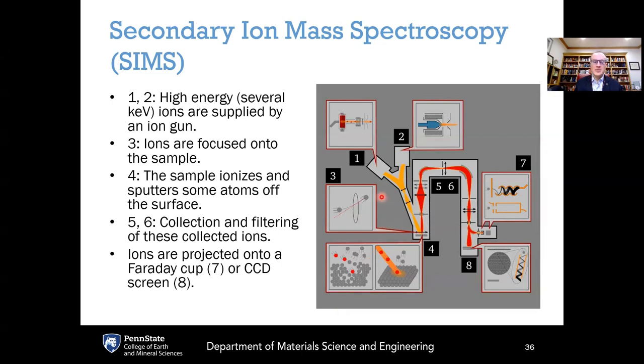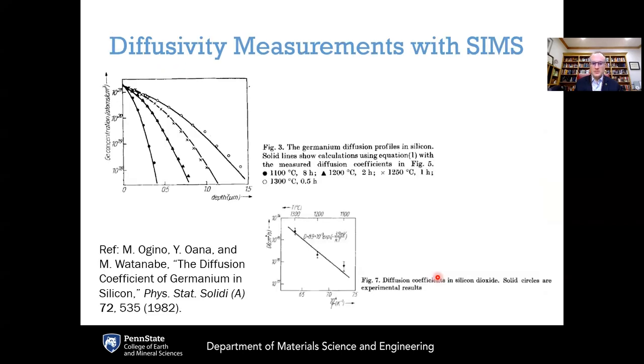This shows a diagram of a typical SIMS setup, where you've got high energy ions, typically several kilo electron volts here. Those are supplied by an ion gun. They bombard the surface here. You can see the primary ions bombarding the surface, releasing secondary ions from the material itself. Those are accelerated here and then separated by their mass to charge ratio. And that is what gives us the spectrum.